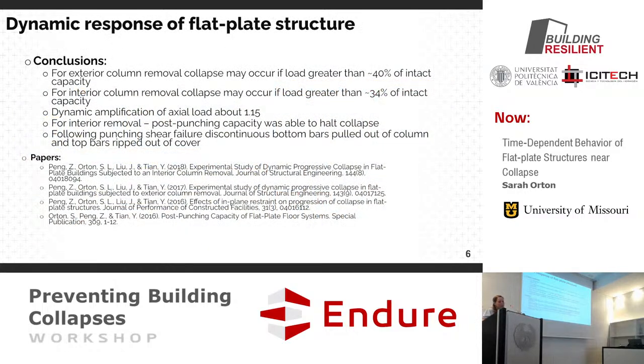So overall conclusions here: for the exterior column collapse, the strength was about 40% of the intact capacity. For the interior, a little bit more controlling there, 34% of the intact capacity. We also found that the dynamic amplification factor was about 1.15. A lot of procedures say to use a value of 2, which comes from structural dynamics. If you have a linear system, that would be the most increase you have from a sudden impact. Because this is acting very non-linearly, the dynamic amplification is actually quite a bit less, and that saves a lot of the structure. You don't have as much amplification.